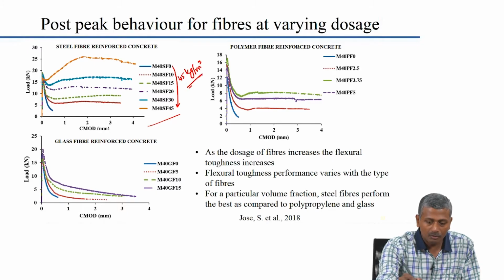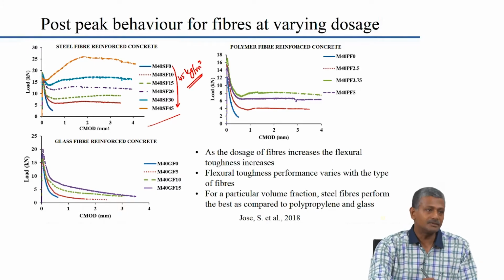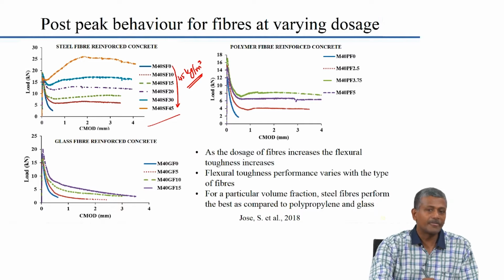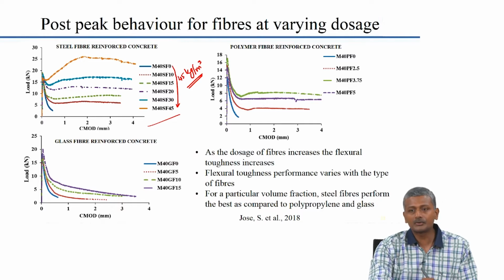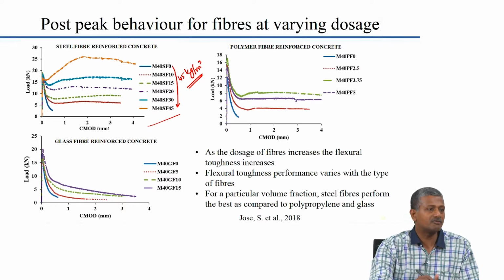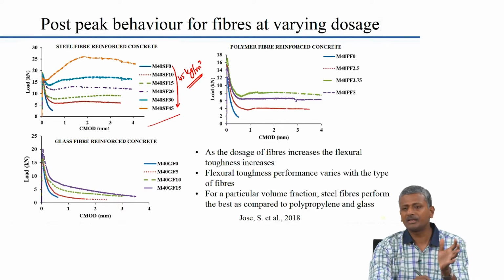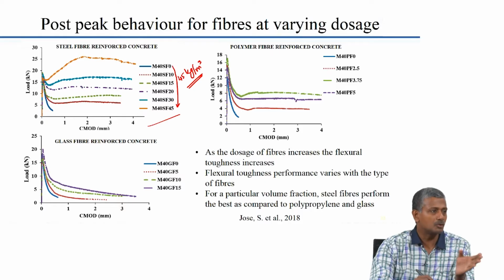Okay. In terms of volume fraction, how much is that? 45 kilograms per cubic meter. The density of steel is what? 8,000 kilograms per cubic meter, right. So, if you have 40 kilograms per cubic meter, that accounts for 0.5% by volume of the concrete. Okay. So, typically fibers are used in that level. When you use steel fibers, you will be using around 0.5 to 1%.